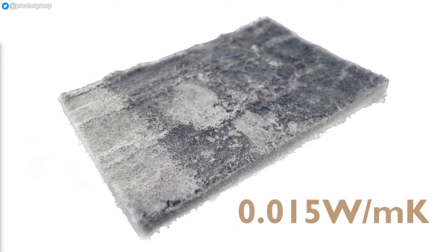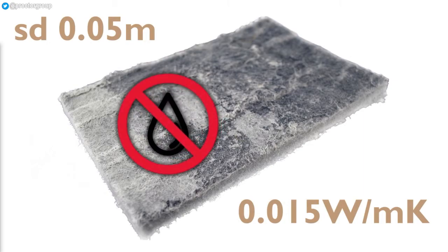The thermal conductivity of 0.015 watts per metre Kelvin makes it among the best thermal insulants in use today, which combined with its high vapour permeability makes it ideal in refurbishments. Spacetherm aerogel is also hydrophobic, meaning it actively repels liquid water.